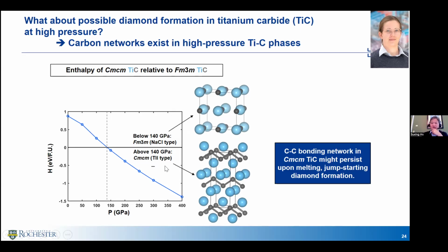To give you some idea, for this titanium carbide system, there was a predicted transition happening at around 140 GPa. Below 140 GPa, you have this Fm3m structure, which looks like this. But above 140 GPa, you have a Cmcm structure, and you can see it has a zigzag carbon layer sandwiched with the titanium layers. So of course, this high pressure phase looks like it will give a strong carbon-carbon bonding already.